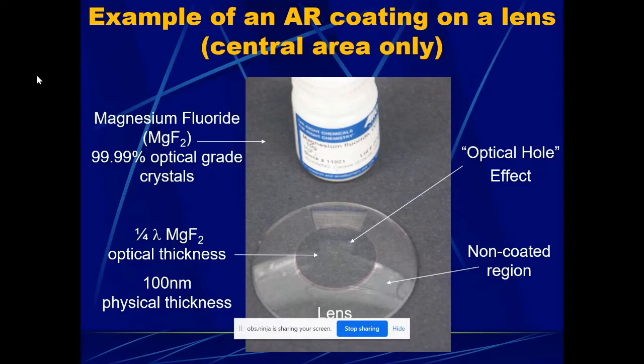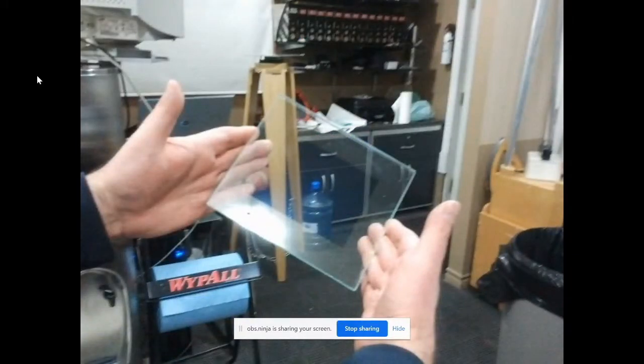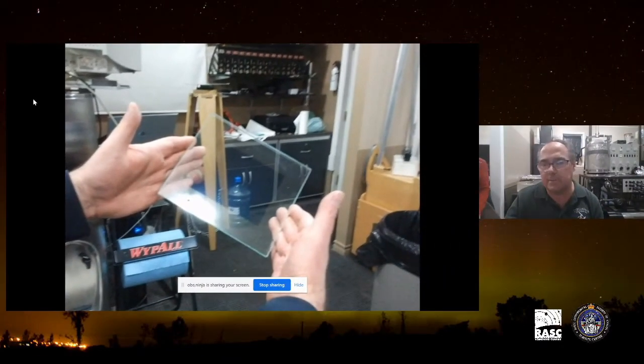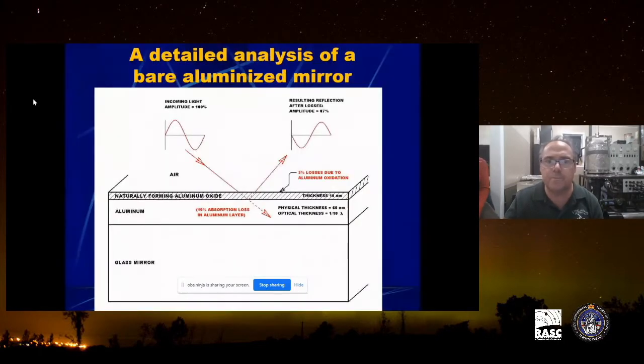The coating is very, very thin. It's about 100 nanometers in physical thickness, but that's all that's required to get this optical hole effect. And here's another piece, a picture frame glass that I used as a demonstration as well. As you can see, the glare off the uncoated section is quite prevalent, but the center part is coated. Now this is just a single-layer anti-reflective coating of magnesium fluoride. Multiple coatings involve many, many layers. Eyeglasses or camera lenses can have five or even more different coatings on them, and they tend to straddle the spectrum to make the glass almost invisible.